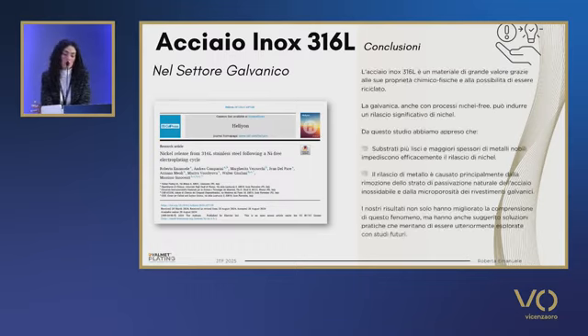To conclude, stainless steel 316L and stainless steel as such is an extremely valuable material. Thanks to its chemical and physical properties, it can be recycled. Galvanic coating, even when nickel-free processes are used, could all the same lead to nickel release. We have to have a polished surface with no roughness. We could use gold as a coating layer so as to reduce the release. The release is indeed caused by the removal of the chromium layer, which is necessary for the covering layer to be in closer connection with the underlying material. So basically, we succeeded in limiting nickel release, understanding also how to better improve in the future.